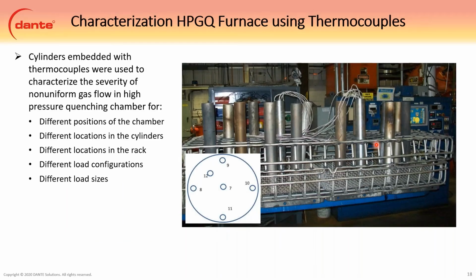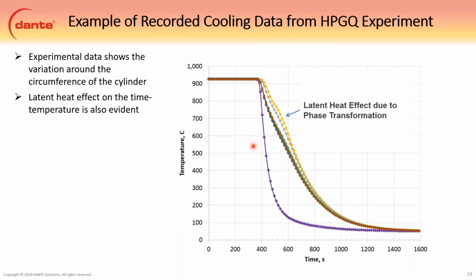This was a high pressure gas quench where we were looking at different positions in the chamber. So these cylinders getting put in different positions, different locations around the cylinder, how the heat transfer varies there. Locations in the rack, different load configurations, and different load sizes. So this was an interesting study, and this is data from there, and you can see the difference. These are the thermocouple temperature measurements that go around the cylinder. So you can see that there's difference circumferentially due to the gas flow. You can also see the bump here. That's from the latent heat during assumed ferrite pearlite transformation.